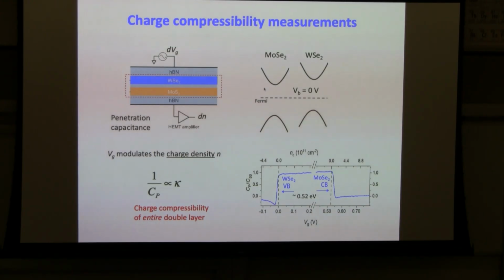Gotcha. So where's it coming from? From the contact. So there's a contact to the middle layer, actually to both of these layers, which is just not shown in this schematic. Because this is the electron layer, this is the hole layer. We are making electron contact to this layer and hole contact to this layer. The gate is in the middle, and then the sample goes out to a larger distance, and there's a grounding electrode. Yes, that provides the reservoir. And in fact, we actually have to engineer the exciton contact carefully in order to let the electron and the hole get in.